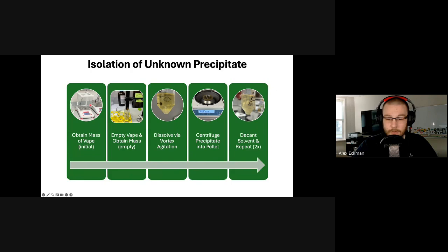So starting off, we obtained the mass of the vape when it was full. We emptied it using gravity over the course of 24 hours. I didn't want to introduce any additional heat or solvent that would further potentially degrade. So simply just caught all of our cannabis oil in a centrifuge tube, dissolved it in some hexane, and as we can see here, that pretty reliably precipitated out any of that unknown. Went ahead and centrifuged the unknown, decanted the solvent, and just repeated that again to wash any cannabinoids or terpenes off of that precipitate pellet.